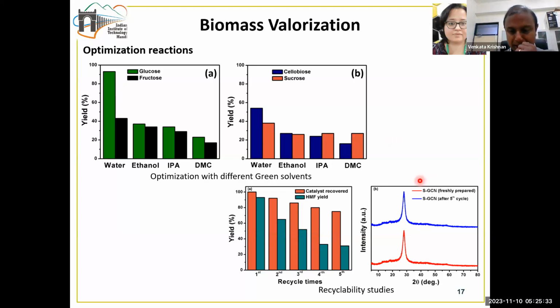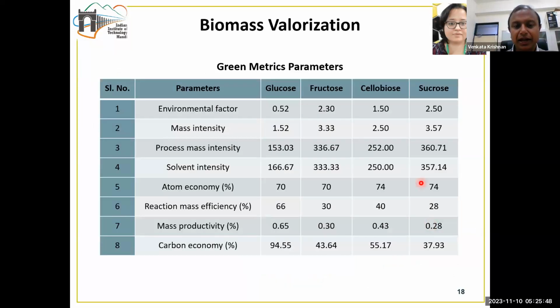Subsequently, we also did a postmortem analysis, wherein we found what the structural integrity of the catalyst is after the reactions, and we found that the catalyst retains its structure after multiple cycles. Then we evaluated the different green metrics parameters, which include the environment factor, mass intensity, process mass intensity, solvent intensity, atom economy, reaction mass efficiency, mass productivity, and carbon economy. And we got very good values for each of these parameters for the different reactants, which include glucose, fructose, cellobiose, and sucrose. All this indicates that our catalyst is green in nature.